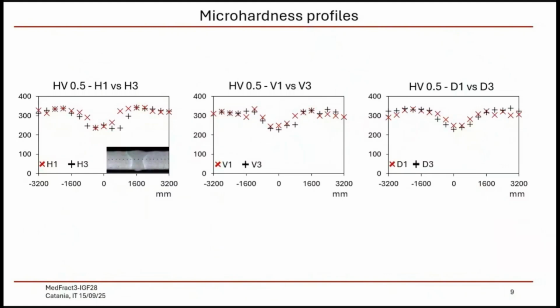These are plots comparing microhardness profiles taken from the middle of the cross-sections of all the BOPs of group 1 and group 3. So again, the main difference is the welding speed. And again, the trend, the profile, doesn't change, is not affected by the building orientation, and it's not affected by the welding processes. The average of the parent material is 320 HV points, which is higher than wrought material because of the fine microstructure. And we have a drop corresponding to the fusion zone, and this is mostly related to the change in the grain size.